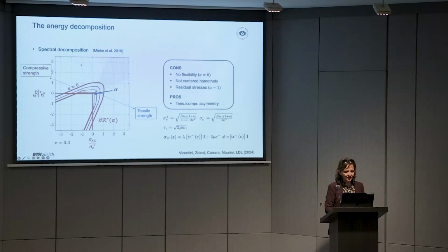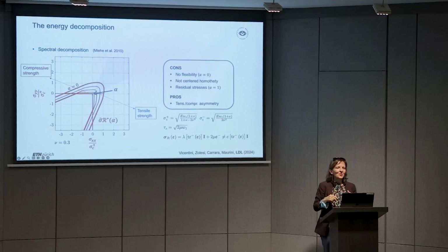Okay, now if we look at the spectral decomposition, this is a little bit funny. So it doesn't always satisfy stress softening. And this is the reason why, by the way, we had this smear damage at the lower right corner of the plate with hole. The tensile strength now is way smaller than the compressive strength, which is good. And this is the reason why in the concrete example that I showed you from the tomograph, we had much less spurious cracks around with this decomposition.